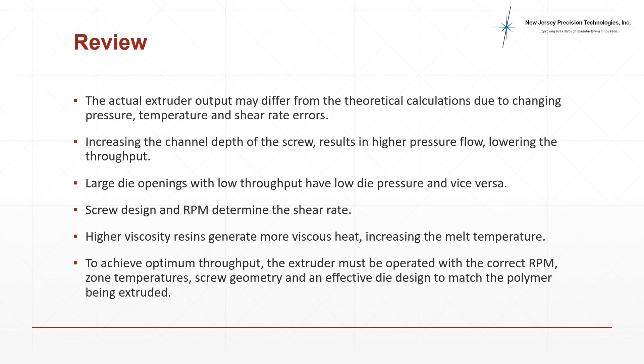In summary, the actual extruder output may differ from the theoretical calculations due to changing pressure, temperature, and shear rate errors. Increasing the channel depth of the screw results in higher pressure flow, lowering the throughput. Large die openings with low throughput have low die pressure and vice versa. Screw design and RPM determine the shear rate.